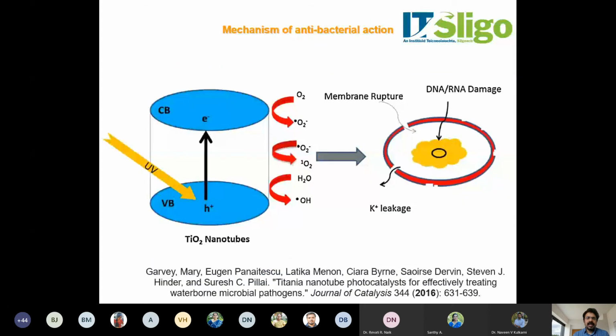So the mechanism again is straightforward, as we discussed earlier. When TiO2 is used, after the irradiation, the electron moves from its valence band to the conduction band. A range of reactive oxygen species are formed, and these react with bacteria, and the membrane can be ruptured, and also it can react with the cell materials, and the bacteria will eventually be killed.